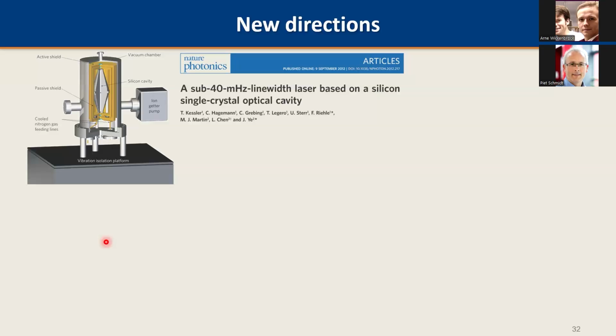The first step was to use materials with a higher mechanical Q factor. I don't want to go into the details, but the higher the mechanical Q, the lower the thermal noise. It has to do with the fluctuation dissipation theorem. Read it if you're interested in it. So people went from glass materials as the spacer material to single crystals, for example silicon single crystal, where luckily you have a transparency window at 1.5 microns, so you can make the mirror substrate also from silicon single crystal, optically bonded onto this football-shaped cavity.